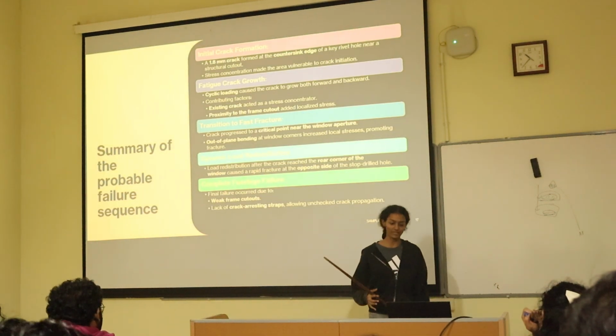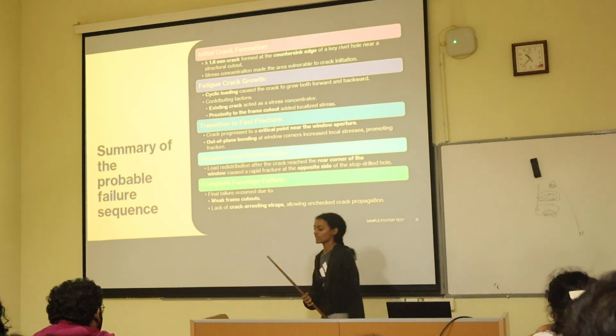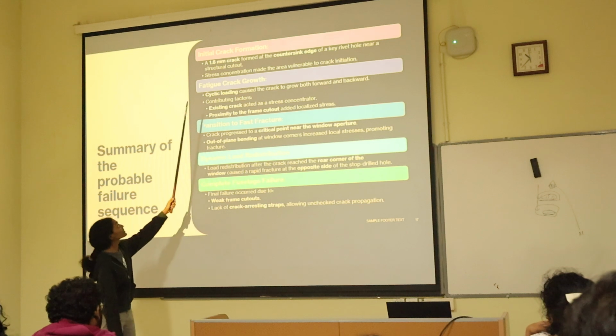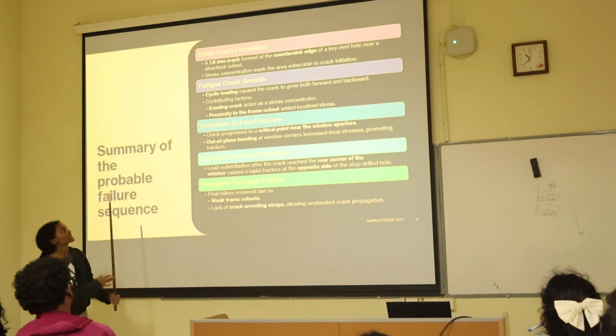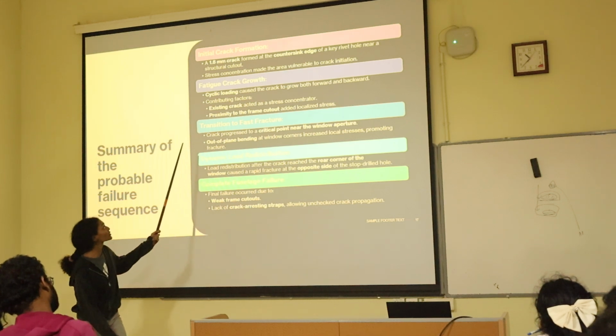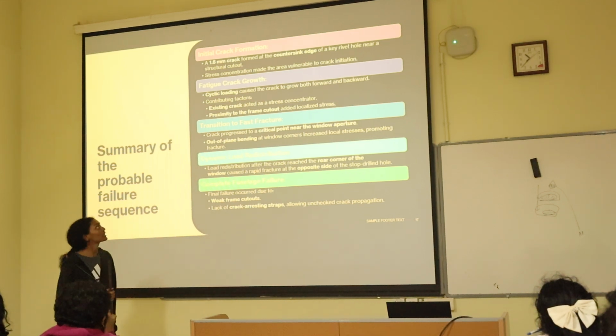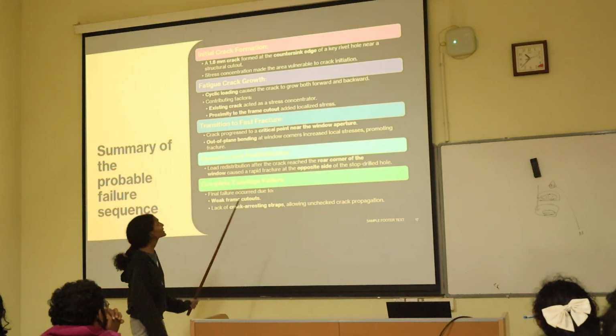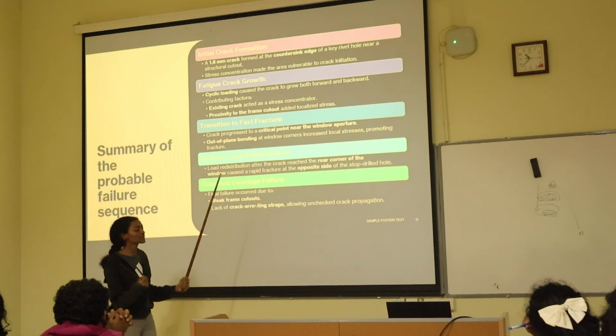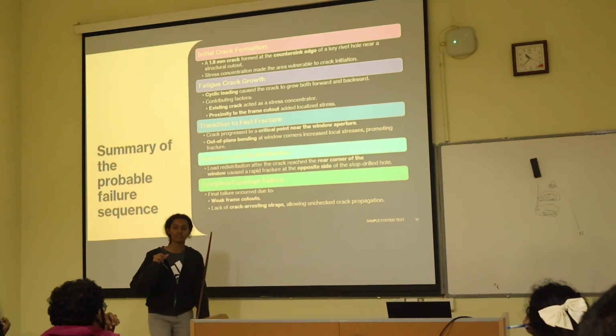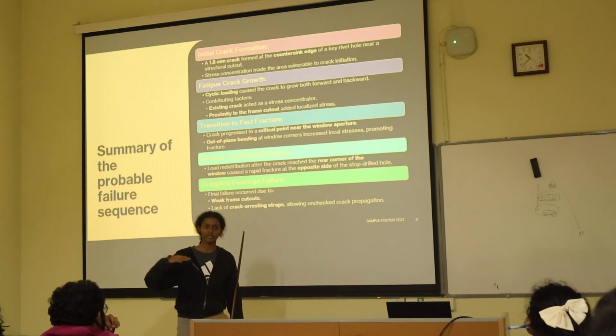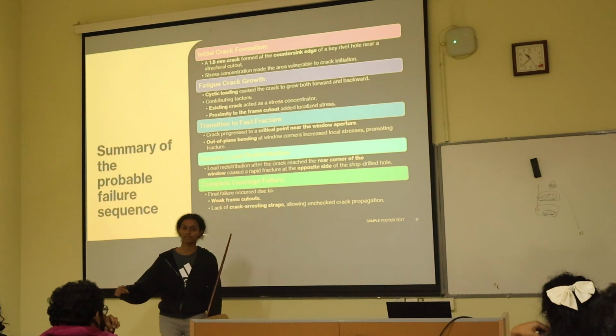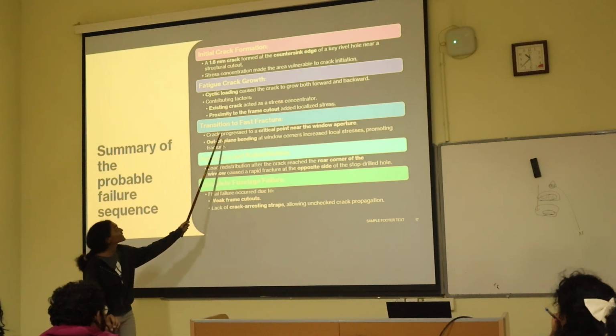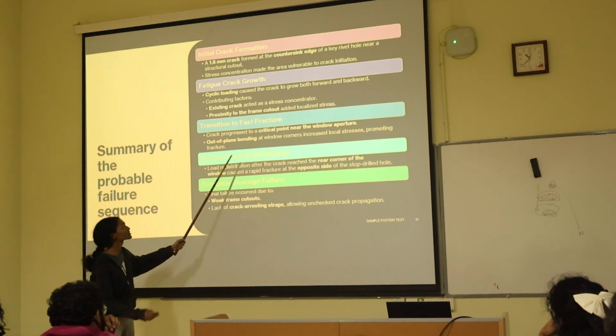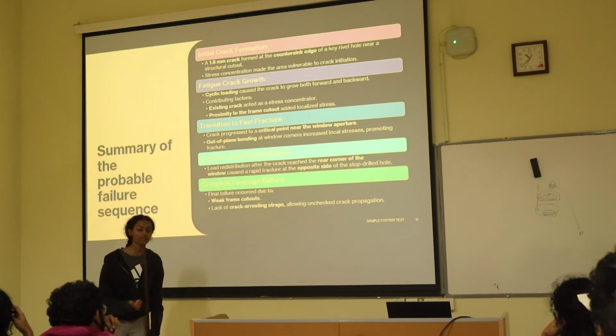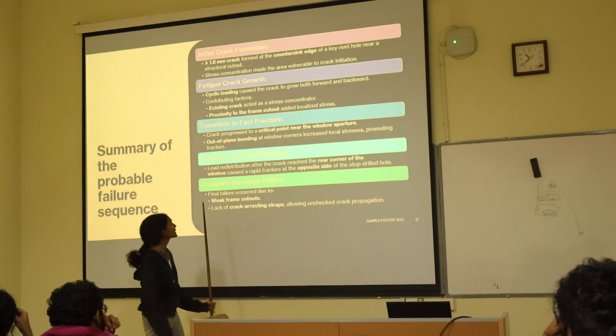Yeah, so this is a summary of all that we have. I'll just say everything. So this is the flowchart. Initially, crack formations occurred around the rivet regions. This was due to repeated cycles, where one cycle accounts for one airplane flight, which includes one takeoff and landing. After fatigue, it transitions to fast fracture. Fast fracture requires very low energy, and it happens catastrophically.